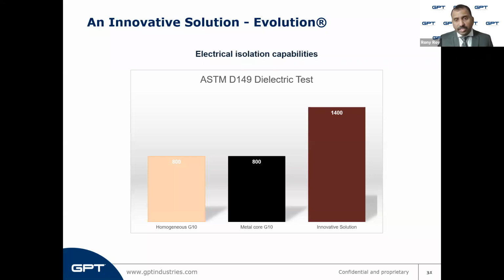The other key factor here is that G10 and G11 will absorb moisture during a hydro test because they are permeating in nature, as we have seen in the previous slides. This significantly reduces the resistance values after a hydro test. I have seen test results ranging from 3 megaohms to 7 megaohms, and many companies in the specs limit the value at 10 megaohms as minimum. And this can be a problem when you're using a G10 based gasket or a G11 based gasket after hydro test. Evolution, since it is a metal core, a complete metal gasket that doesn't have any plastic laminates on it, doesn't permeate, and even after hydro test, the typical dielectric or resistance readings are in the gigaohms range.